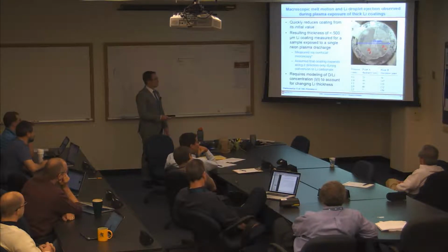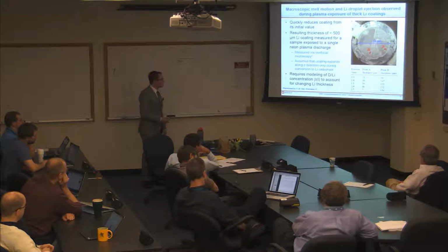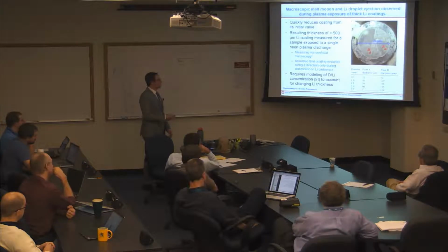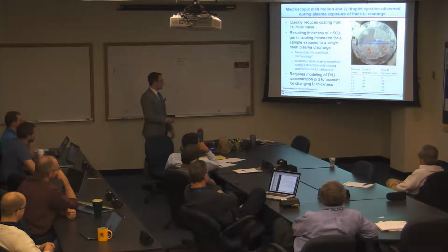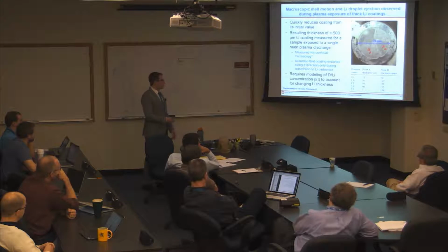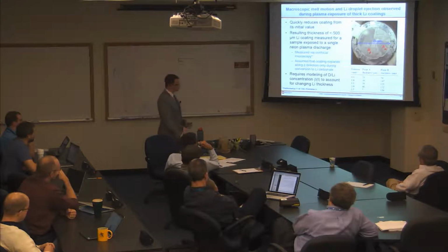And what I did, or I didn't do it, this was done by a colleague, Yawen Ye, who scanned across the surface from points A and points B in 500 micron increments, and basically found that the coating was very strongly reduced from its initial thickness of 500 microns. And it varied a lot, actually, from anywhere from about 10 microns to 150 microns, something like that. So basically, what this implies is that you need to model the deuterium lithium concentration as a function of time and temperature for some changing lithium thickness, which is a bit more complicated.